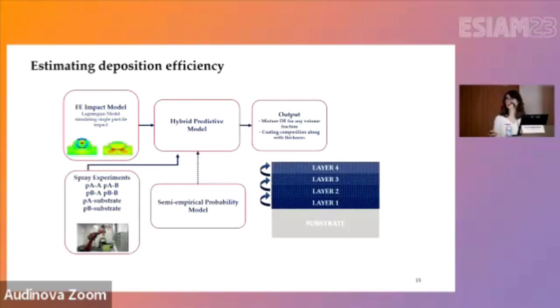And then we have developed a semi-empirical probability-based method that would bring all together in order to give us the possibility of estimating the deposition efficiency in terms of volume fraction of each material that we have in the deposit, and its variation as we are getting far from the substrate. Close to the substrate, we have also the interaction with the substrate, so we have a transient condition in terms of chemical composition, and as we get far from that, the chemical composition becomes more stable.